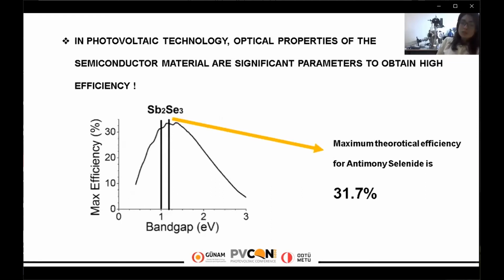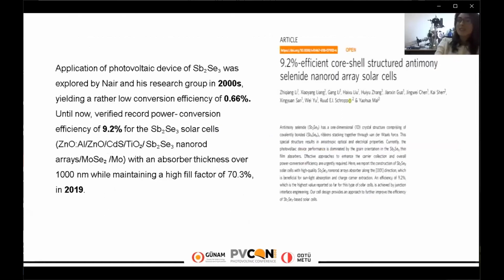As we know, in photovoltaic technology, the optical property of the semiconductor material, the material used in the stack order as a P-type material, is very significant to obtain high efficiency. And here we see the antimony selenide maximum theoretical efficiency calculated as 31.7%. It's really great. Here we see the article with the highest efficiency until now, a 9.2% antimony selenide solar cell.